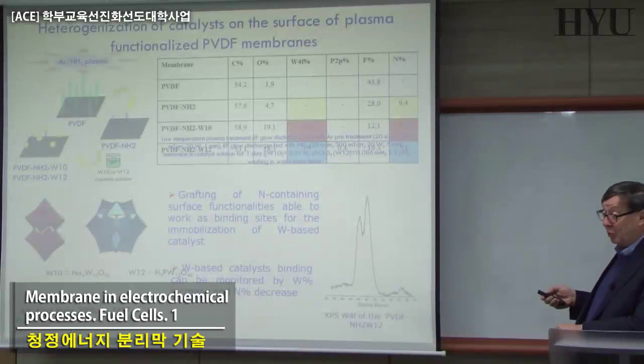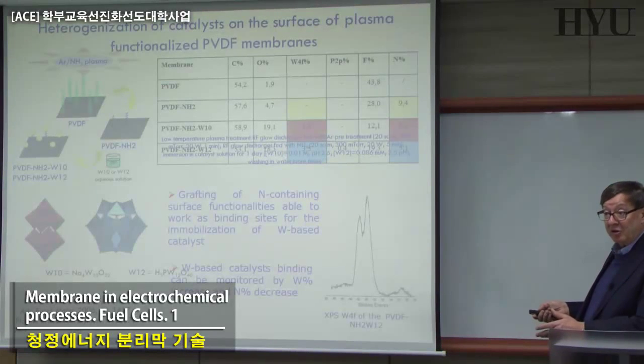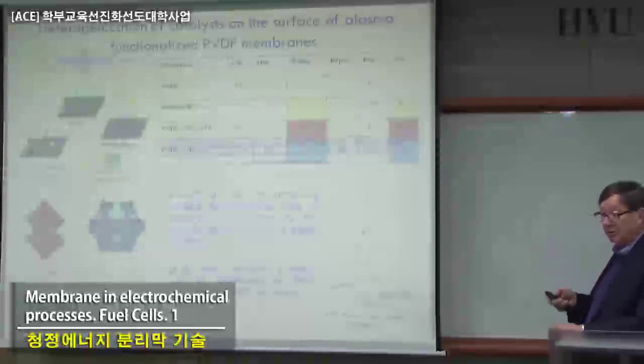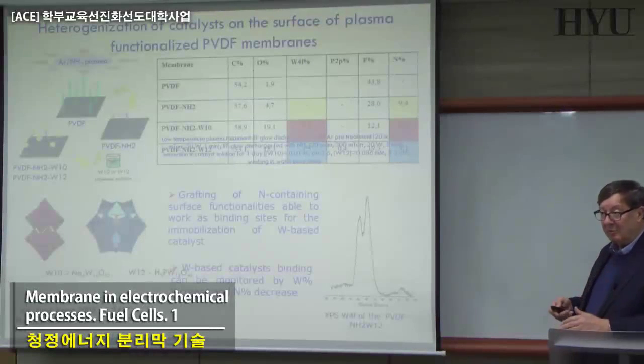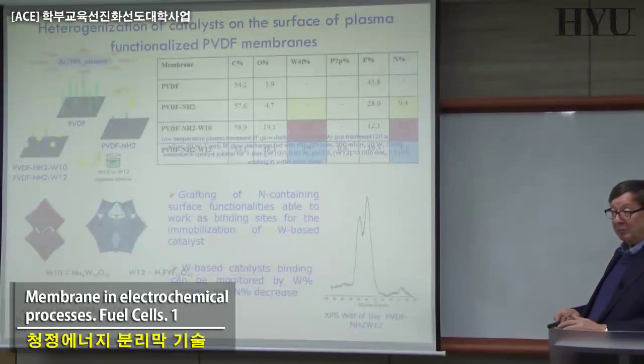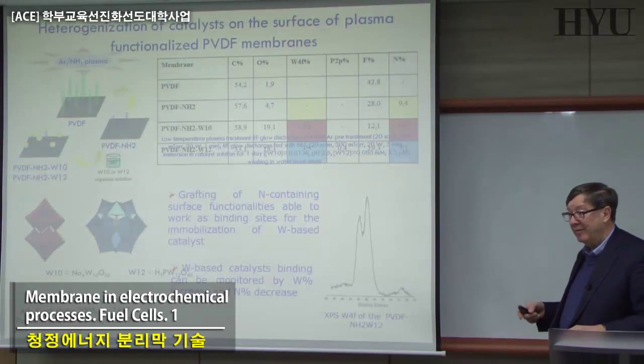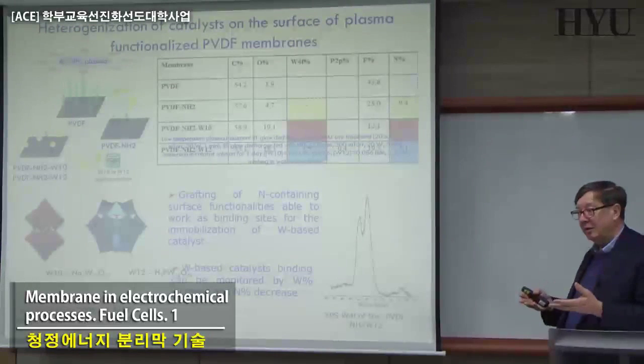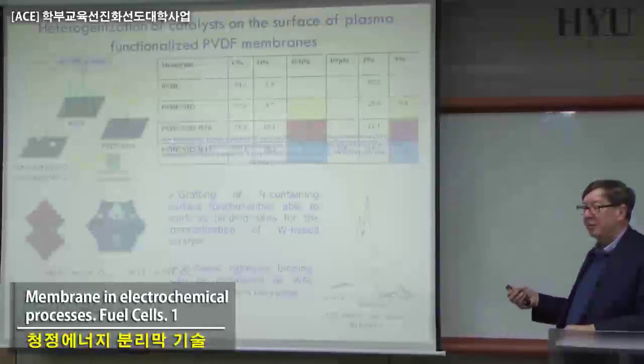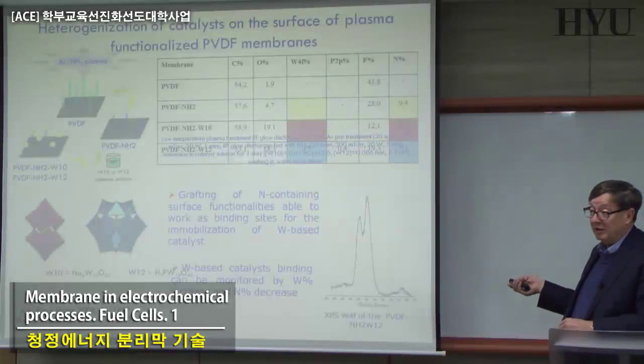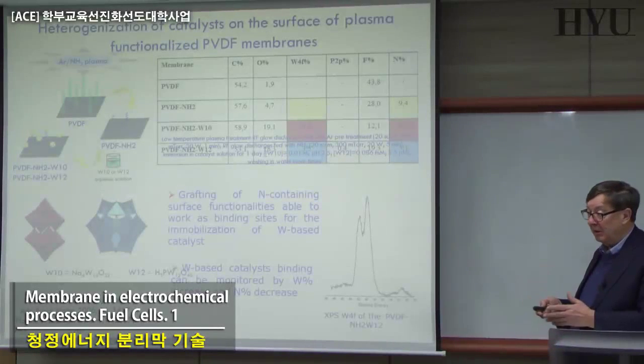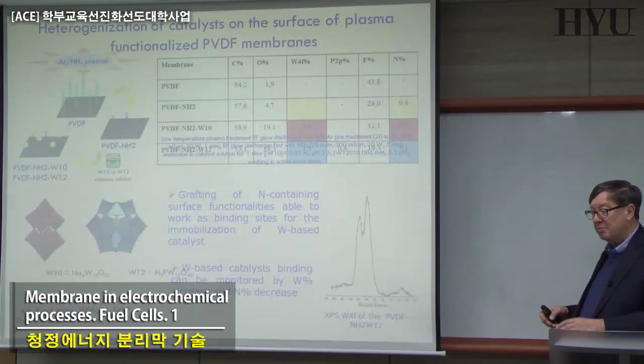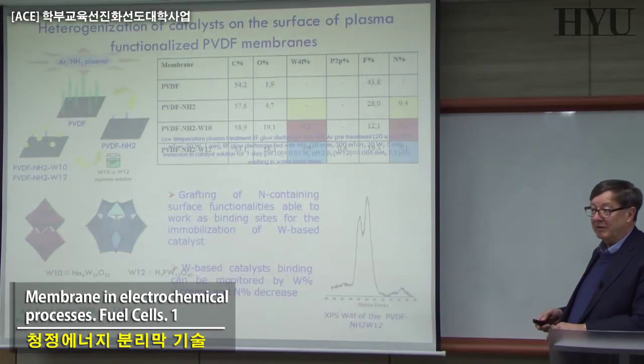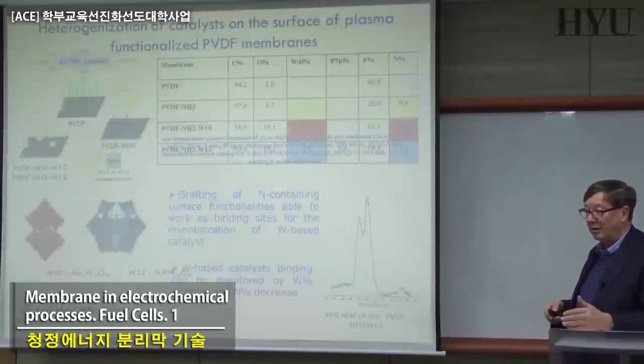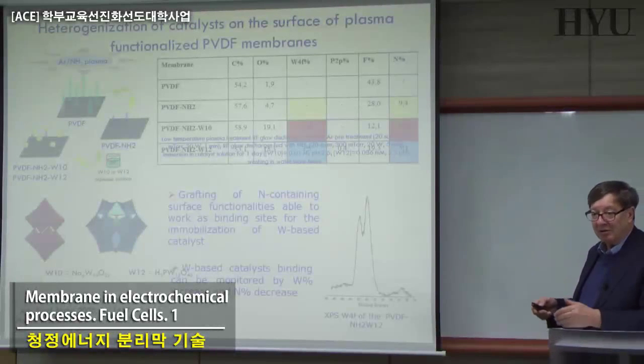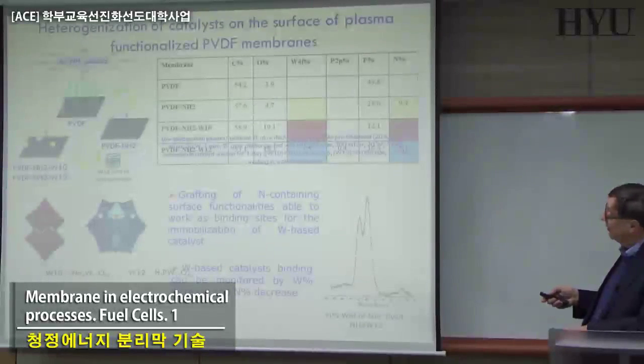You can also have different ways of doing this, just by using phase inversion, basically. You can make this kind of membranes by using the same properties that some of you are studying today. PVDF is the same polymer, and some of you are adding additives for increasing porosity, pore-forming additives. And instead of this substance, you can use a catalyst, but the methodology is the same. Basically, what you expect at the end, increasing the percent of the additive, can be a catalyst, can be a pore-forming material, can be something different, the story is the same. And so you can have this kind of effect.